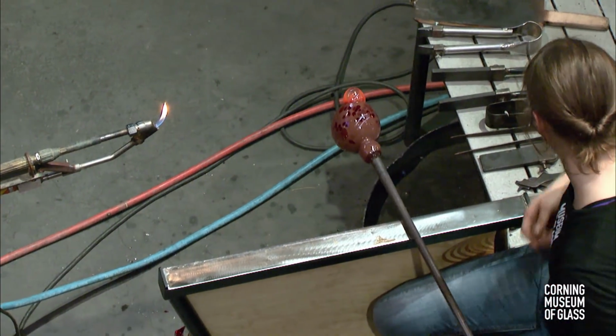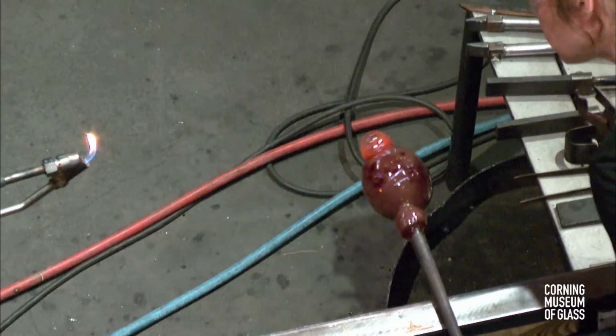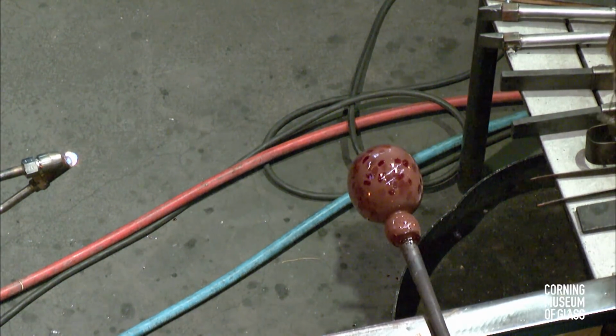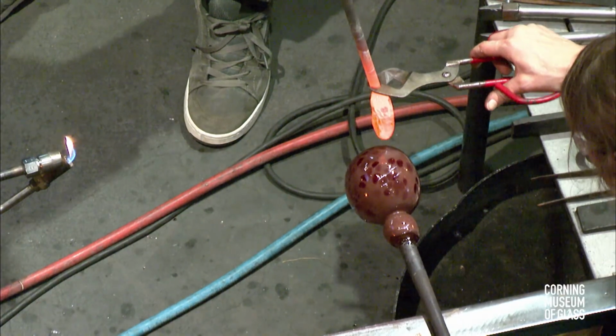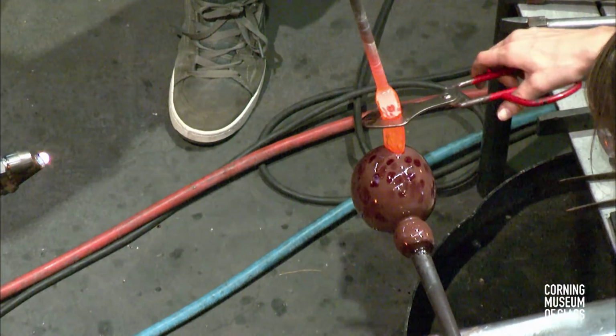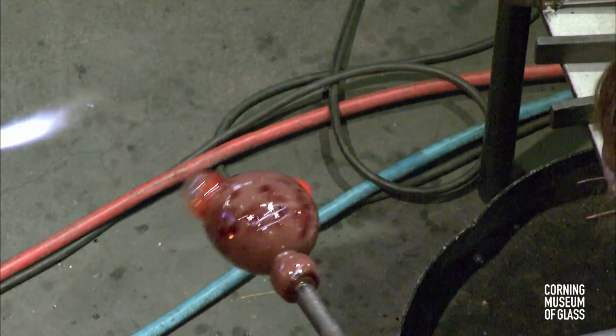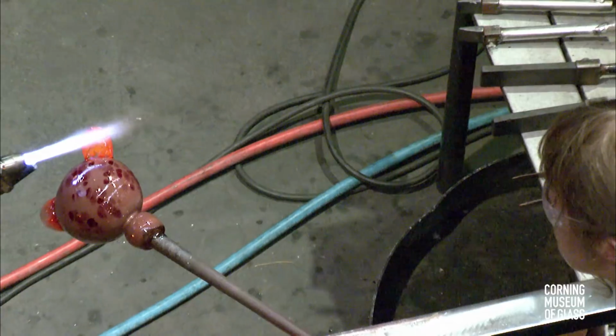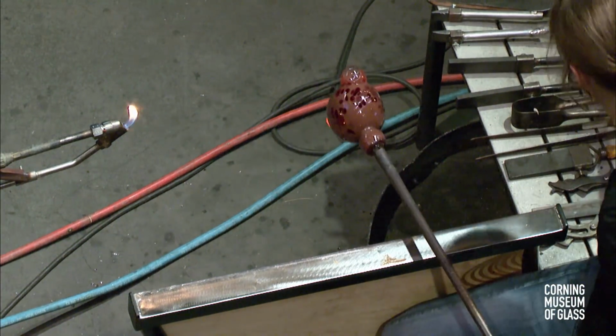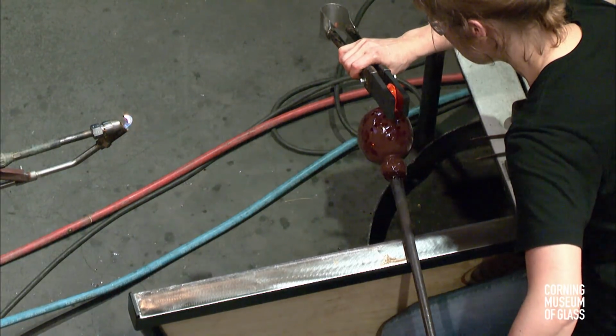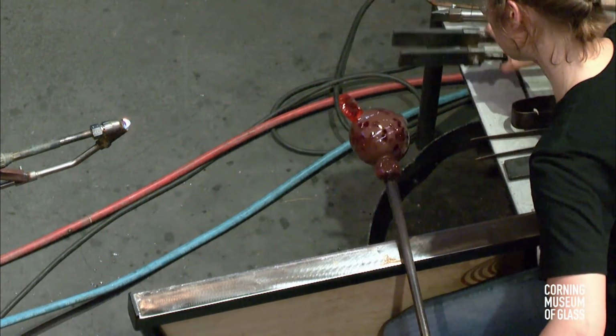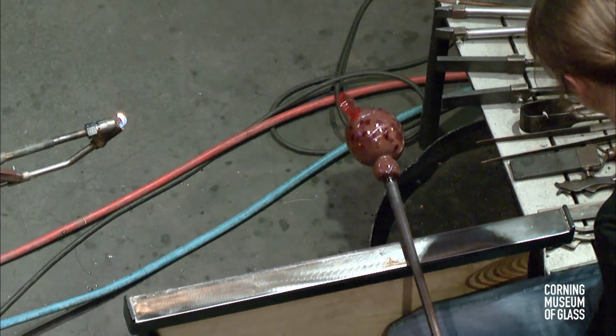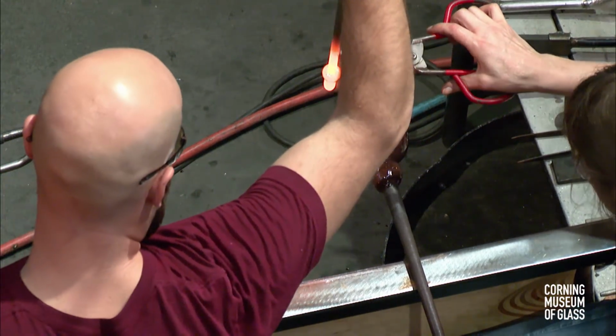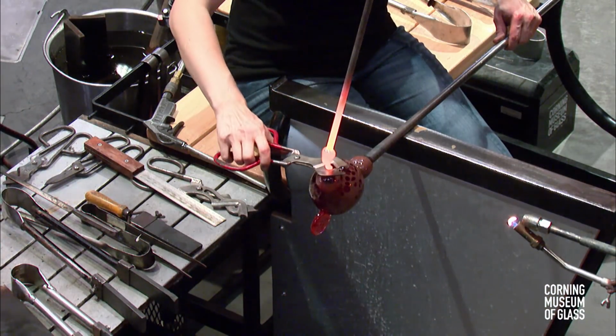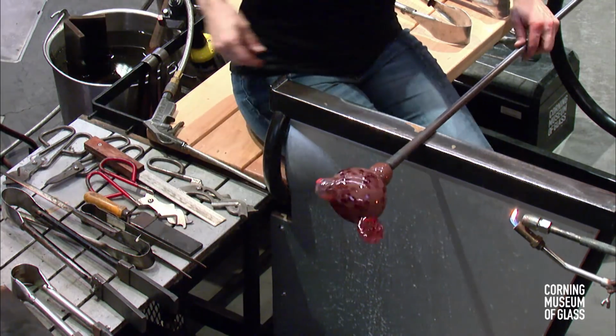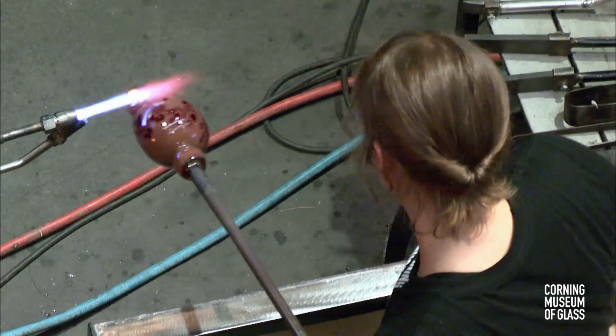So you see they kind of preheat where they're going to add the little bits of glass. They hit that with a torch, and then they add that bit. So the connection of these additive bits ends up being really, really hot, and that makes a really, really strong connection. They're adding on the tail of the happy chicken right now, and you couldn't really break the tail free from the body of the piece without totally destroying the piece. So the strength of a glass-to-glass connection is dictated by the temperature of the connection. The hotter a connection is, the stronger it will be.